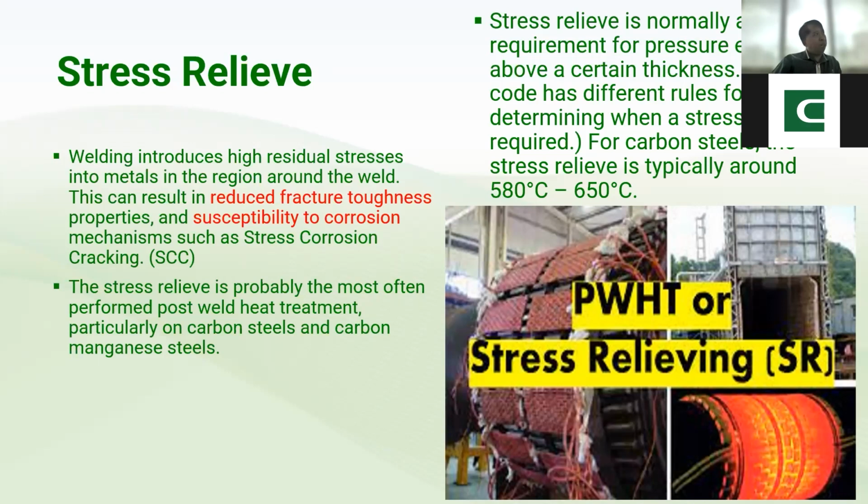And usually for carbon steel, this stress relieving soaking temperature is between mga 580 to 650 or yung exact is 593 to 649 degrees centigrade.